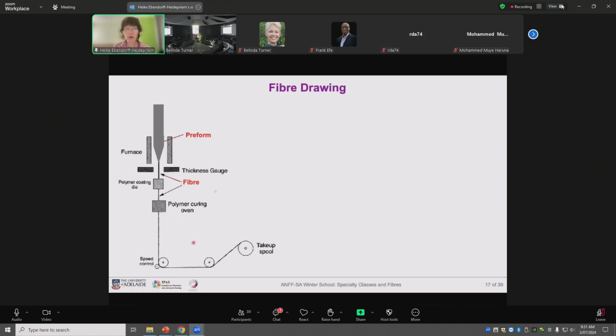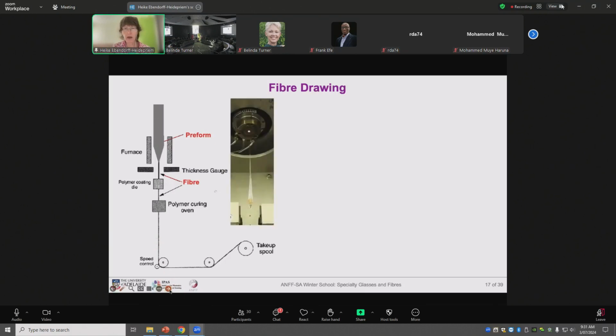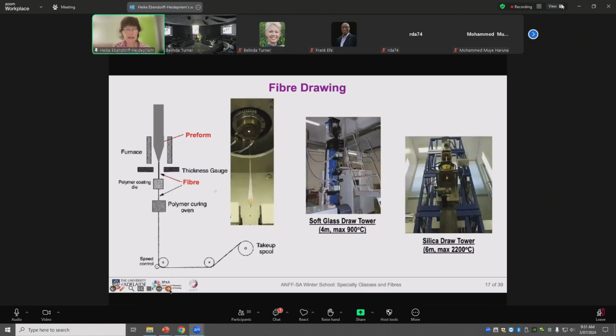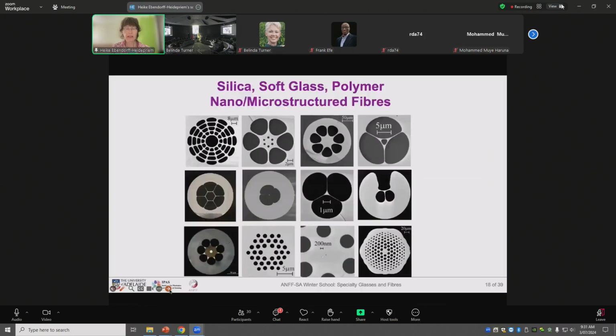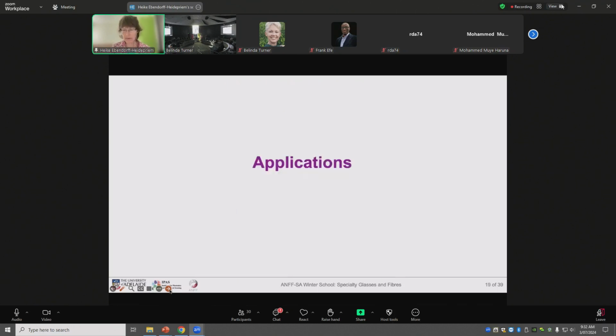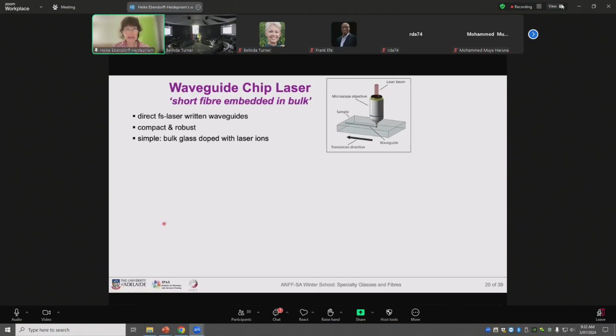Fiber drawing is taking the preform and stretching it down to a fiber with in the order of 0.1 to 0.2 millimeter outer diameter. We have two fiber draw towers, for soft glass and for silica. Here you see a range of structures we made out of polymer, soft glasses and silica. I won't go into details because I want to use the little time I have left for a few applications.